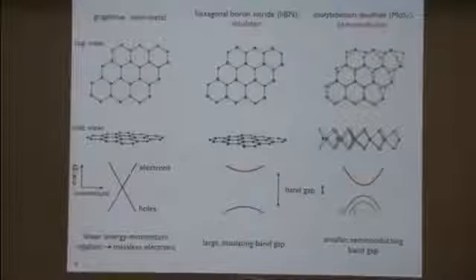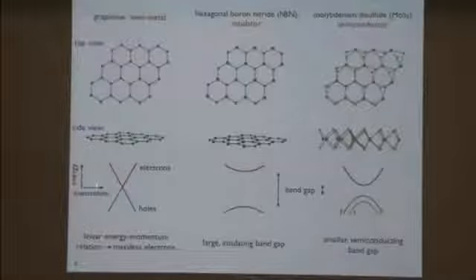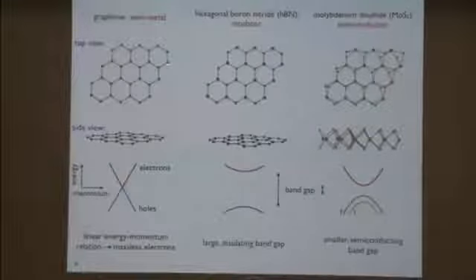So I'd like to say a little bit about the properties of these various things. Graphene, the semi-metal, has probably the most unique properties of these three. It has an energy-momentum relationship which is linear, that makes the electrons in this material behave as if they're massless. Hexagonal boron nitride has a structure that's identical to graphene's, except that each of the carbon atoms are replaced by alternating atoms of boron and nitrogen. And that gives it a very large band gap, so it's an excellent insulator. The band gap is just the separation in energy between the electrons in the conduction band and the holes in the valence band.